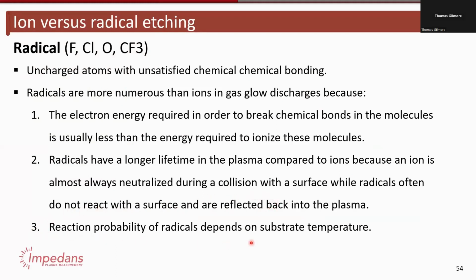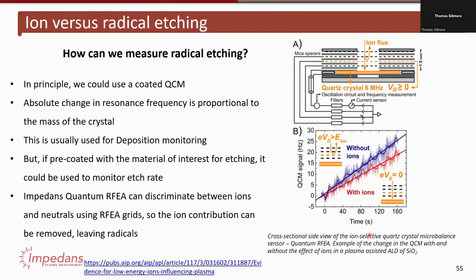One notice that the reaction probability does depend on substrate temperature. So what's the concept? This is just a concept. What happens if we use a coated quartz crystal microbalance? With a quartz crystal microbalance, the absolute change in resonance frequency is proportional to the mass of the crystal. Usually they're used for deposition. As you deposit, the crystal frequency changes, and there are some models that turn that into layer thickness and deposition rates.